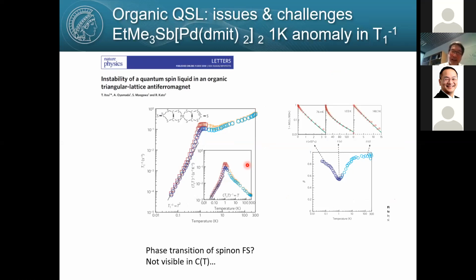So far so good, but to be fair, there remain some issues with this organic quantum spin liquid. First of all, in those quantum spin liquids, there is some signature of phase transition, anomalies, which we don't know the reason for. Like this NMR 1 over T1, the nuclear relaxation rate, shows a very clear anomaly. And the nuclear decay curve also shows some anomaly around this. So there seems to be some sort of phase transition, which could be related to the spinon Fermi surface.